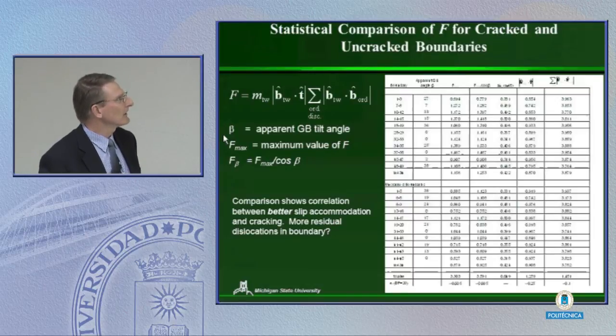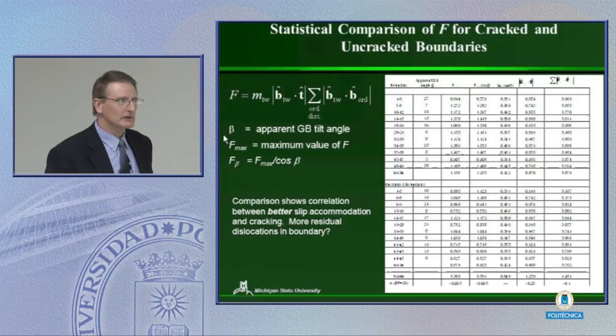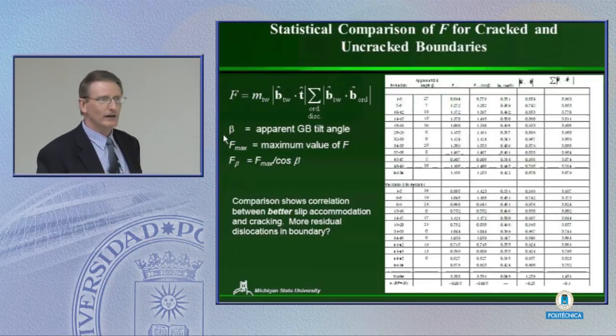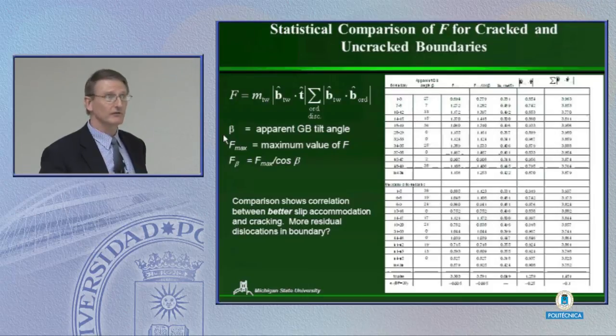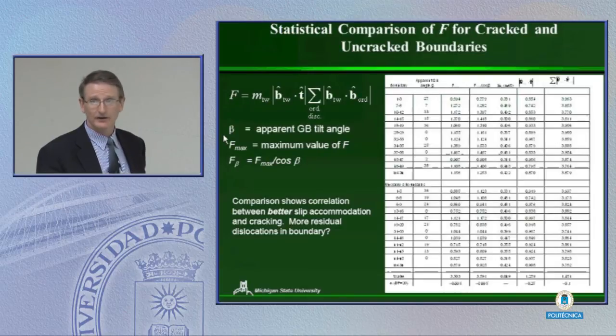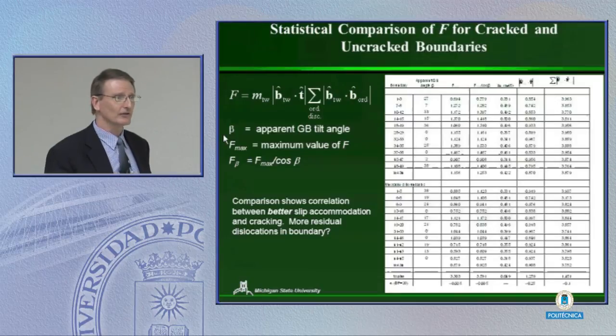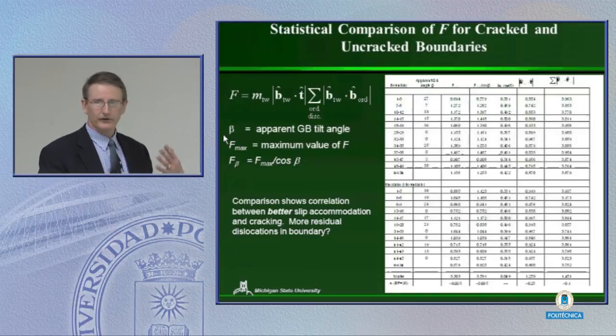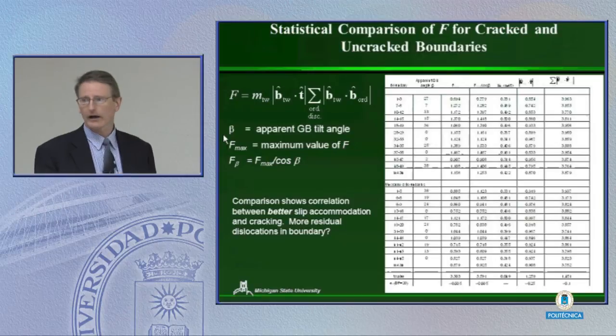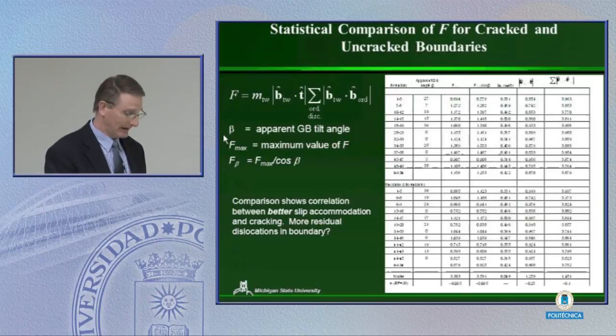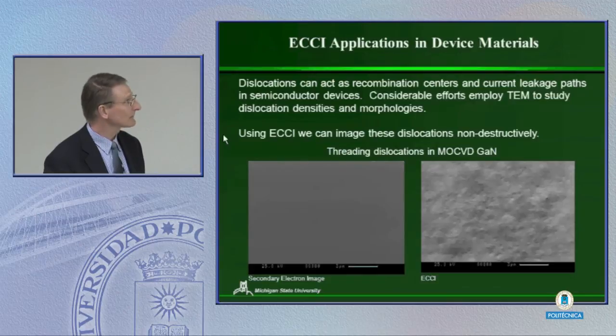The most interesting thing, though, is if we look at the individual factors associated with this, and we do the same sorts of tests, we see that the probability doesn't break out the same way. So really what it says is that the boundary cracking we're seeing here is a function of multiple variables that are involved. I guess it shouldn't be a surprise to anyone, but it also means that whenever you go to any material, you've really got to look at a lot of the details and the crystallography and how things interact to really understand why some boundaries may fracture and why some boundaries may not fracture. It's not a simple process.